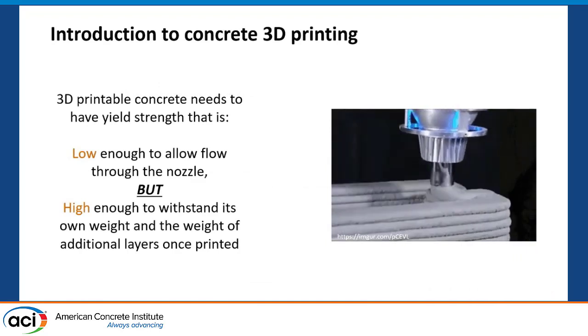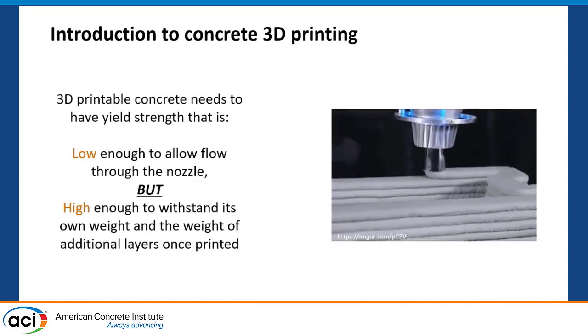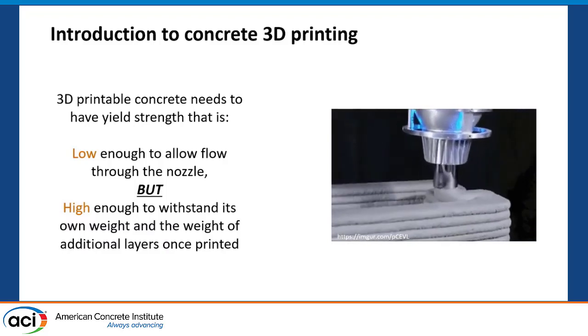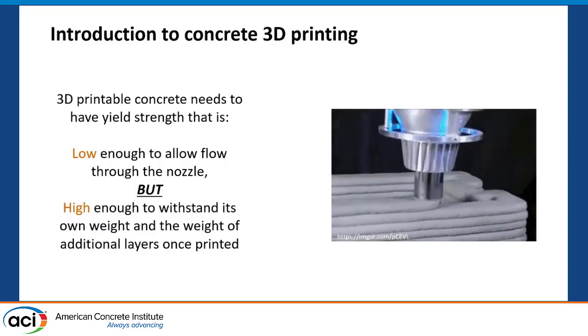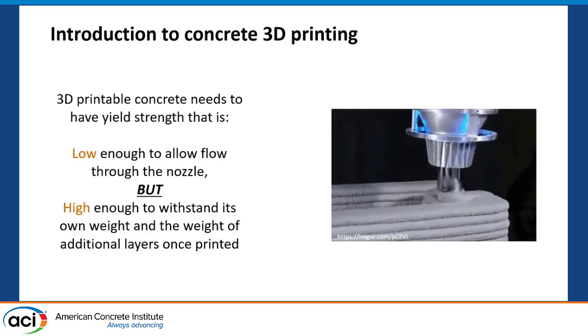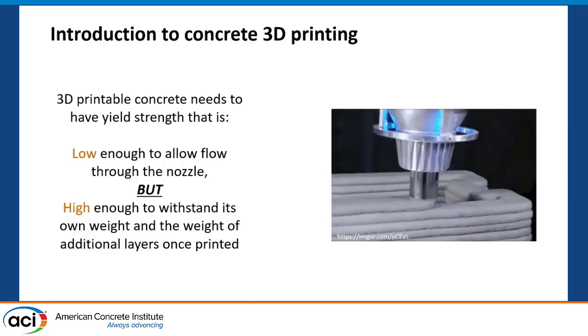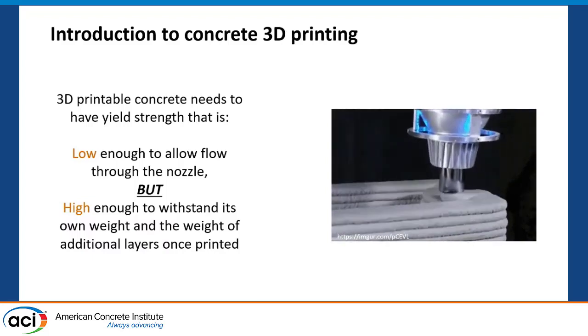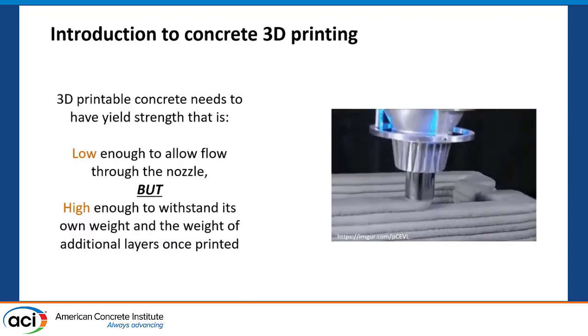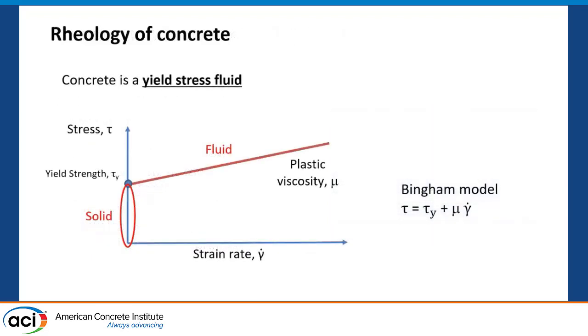There is a need for a certain kind of rheological duality when you are 3D printing. You want a material which can flow through the printer and exit the nozzle, but then you also want it to be a solid so that it retains its shape and can take the weight of layers placed on it subsequently. Thankfully, concrete is a yield stress fluid where the stress acting on the material decides its state. If the stress is greater than its yield strength, it can behave like a fluid, and it can also behave like a solid if the stress acting on it is less than its yield strength.